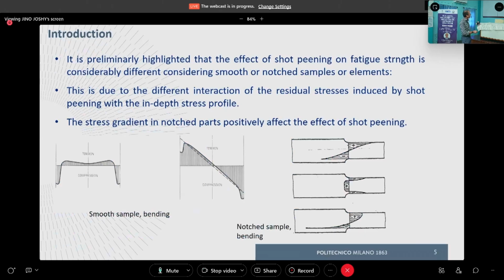Here we see the same bar in bending. The straight dashed line represents the trend of the applied stress due to bending, the nominal stress, the typical linear trend, maximum on the free surface, going to 0 on the axis, and then going into compression on the other part of the cross section. Then we superimpose the residual stress on this linear trend, and we see that this is the overall, global stress trend. What can we notice here? It's true that where we have the maximum tensile stress, we are reducing the stress. We are inducing an improvement of the strength.